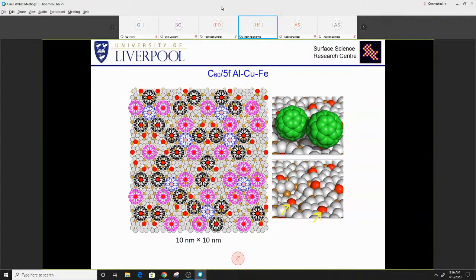And this is because there's an electron transfer. There's no theoretical calculation yet, but the thing is that there is electron transfer between iron and the molecule, and still interaction between iron or manganese with it. Again, here if you compare the size of the molecules and the distance between the atoms, right? They are comparable. So we think that both electron transfer and the size of the molecule are the governing factors for the output of such a complex molecular array.